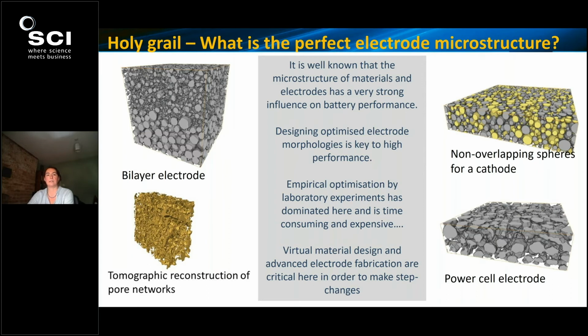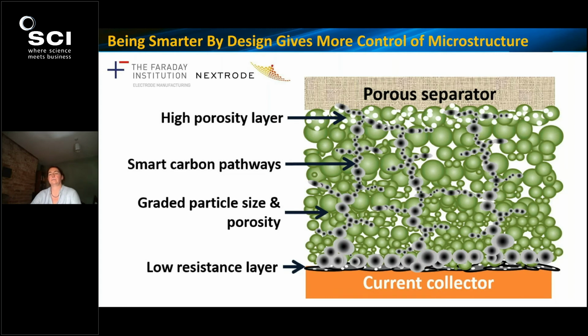have their microstructures optimized. So some recently interesting projects in the Faraday Institution repertoire, Nextrode for example, are looking at graded electrodes, whereby you can deliberately put down different materials in a gradient of composition and porosity to try to design the perfect functional microstructure, whereby, for example, lower resistance layers nearer the current collector, different types of porosity gradients nearer the separator, particle size to have a more efficient packing density without compromising the penetration of electrolyte.